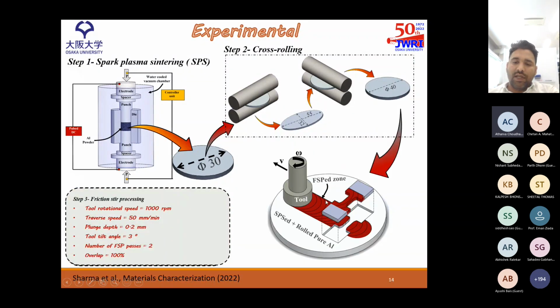Now, friction stir processing: this is a pure aluminum billet formed by spark plasma sintering, and we have done the processing with two passes, and we obtained a tensile specimen such that the whole processing zone comes under the gauge length. We used process parameters like 1000 RPM and a traverse speed of 50 millimeter per minute. We want to use this technique for graphene and carbon nanotube composite.